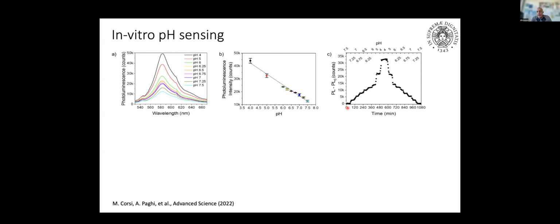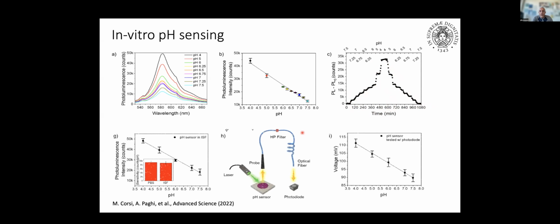You can see here the reliability over time, a time-resolved PL curve versus pH value. When the pH decreases, the intensity increases, and when the pH goes back, the intensity goes back, and there is no significant hysteresis. We demonstrate that it's possible to monitor the sensor not just with a spectrometer, but also using an LED and a photodiode to measure the integrated intensity. Then we can use a simple electrical circuit to convert the photodiode intensity into a voltage over pH with good results.